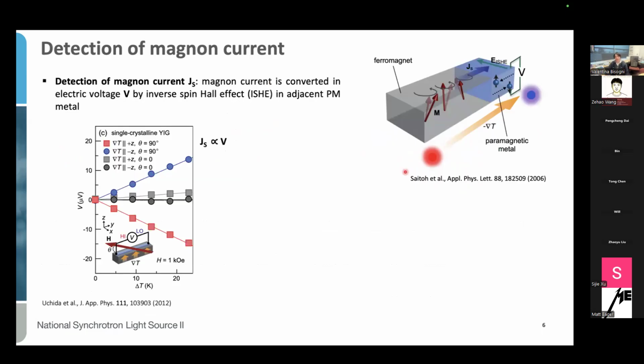As it regards instead the measurement of magnon current, the most common approach that we can find is based on the inverse spin Hall effect. So we can refer to the picture here on the right, where we have our magnetic conductor with a spin current inside. And now to detect the spin current, the most used approach is actually to create an interface with, again, a metallic material that is non-magnetic, and usually can be platinum again. And now the spin current gets injected into the platinum, and by inverse spin Hall effect, it is now converted into an electrical signal, like this voltage here.